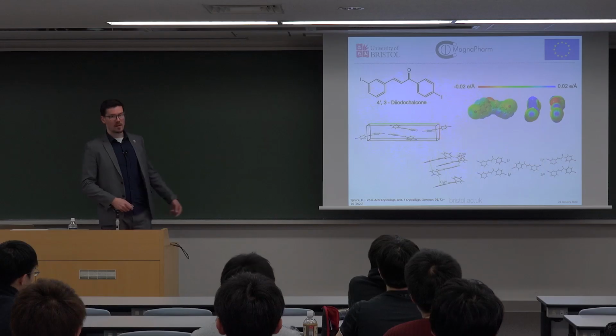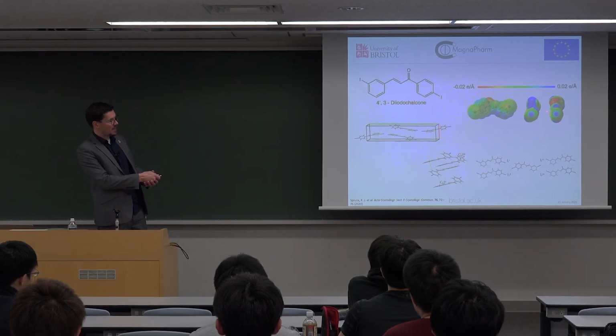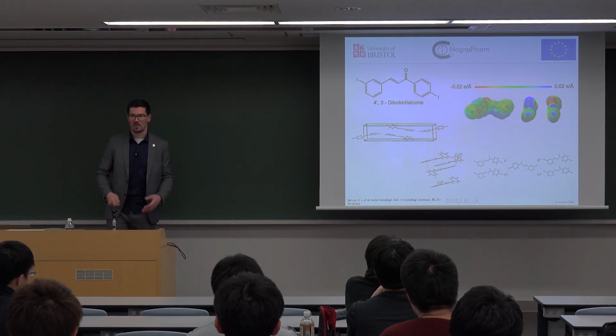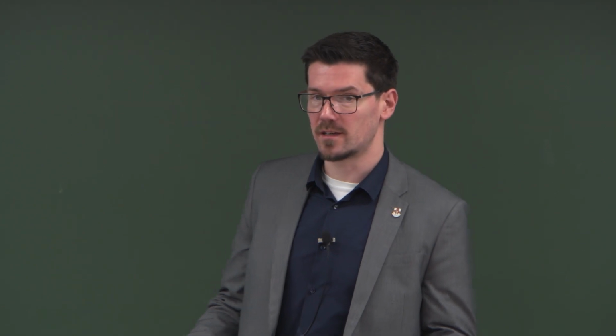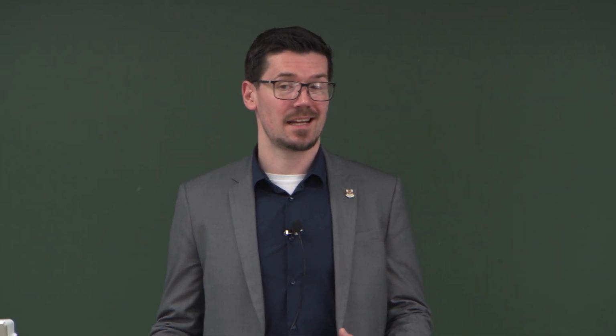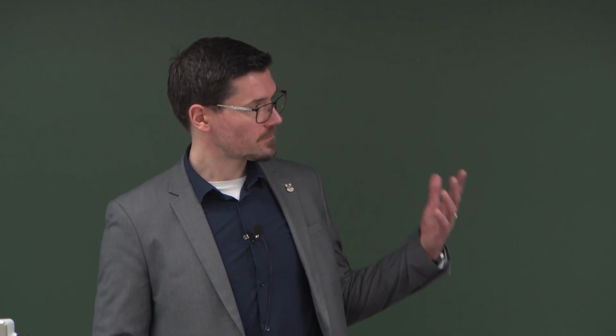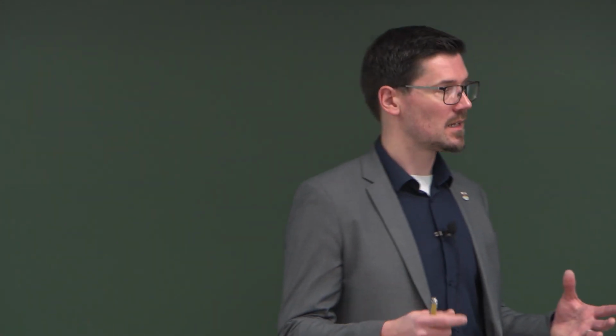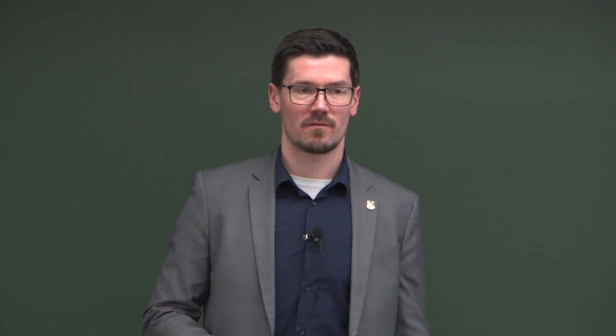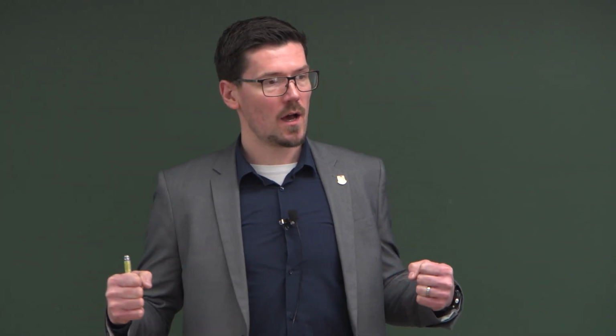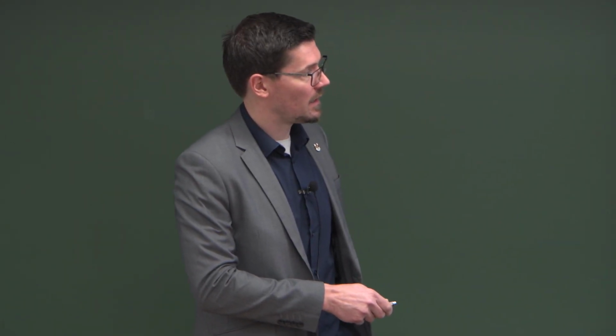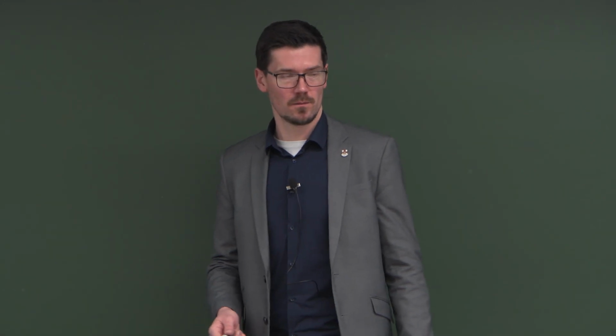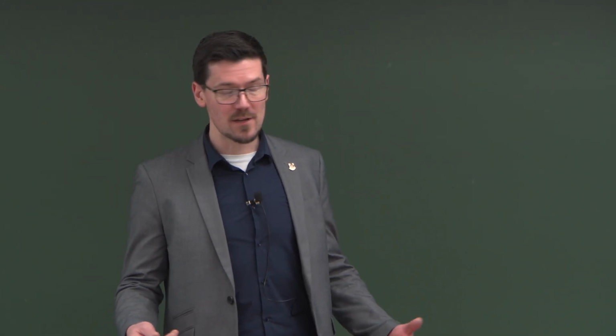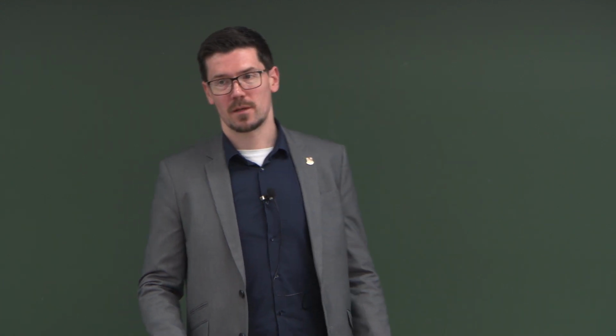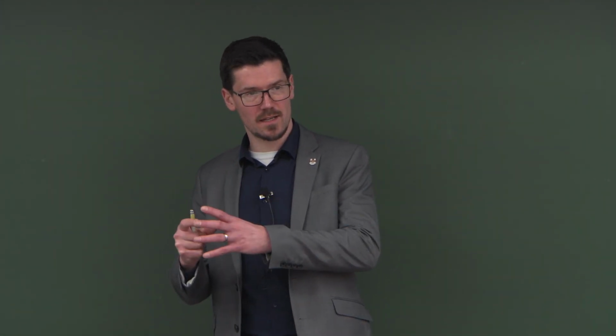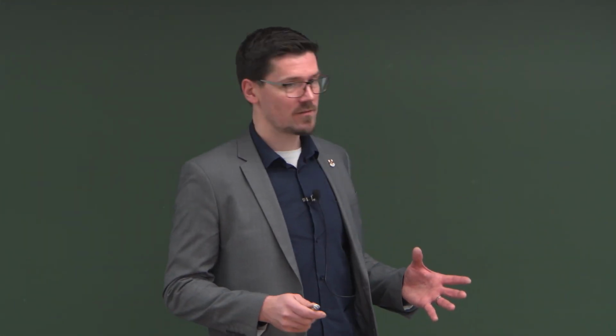If we look end-on to these molecules, we can see here, we've got these little blue spots of slightly electropositive region. This is a fairly interesting interaction that is commonly seen in halogens, especially iodine. What's happening is, because iodine is so electron dense, if you attach it to an electron withdrawing group like the aromatic ring, what happens is it pulls that charge away from the iodine enough to expose a little positive region, and that's called a sigma hole. And the reason that's interesting with molecular crystals is because you then have a single atom which is partially electropositive and around the outside partially electronegative.